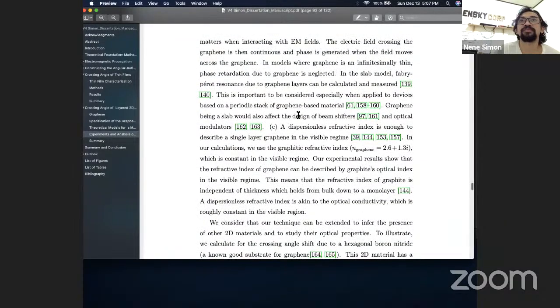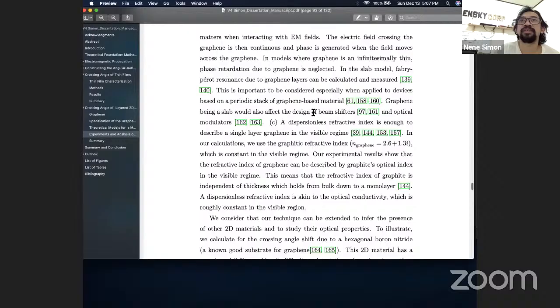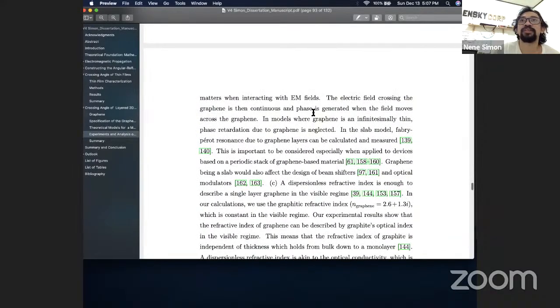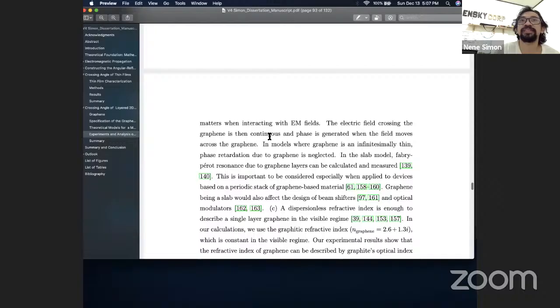Also, it means that you can have a Fabry-Perot resonance due to graphene layers. So a single layer graphene is a slab according to our experiment. And if it is a slab, it has thickness, so it can demonstrate Fabry-Perot resonances. And if you are going to create devices based on graphene, you need to take into account that a graphene layer can give Fabry-Perot resonance. And also, it means that the electric field is continuous through the boundary.